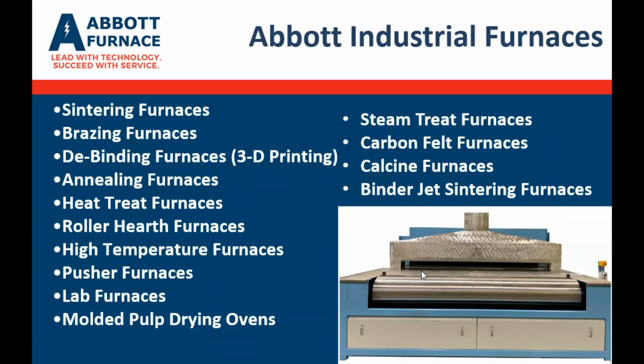As far as the various furnaces and processes that Abbott handles, we're well known for our sintering furnaces, being located in a very large population of powder metal customers, a variety of brazing applications, debinding furnaces for the 3D printing and additive market, and of course annealing and heat treating. We're known for our continuous belts, but we also do a lot of roller hearth type furnaces, high temperature furnaces, and lab furnaces. As you see in the photo there, it's molded pulp drying ovens for items such as egg cartons, to dry them into shape. Also steam treating, carbon felt, calcined furnaces, and binder jet furnaces for the additive market.